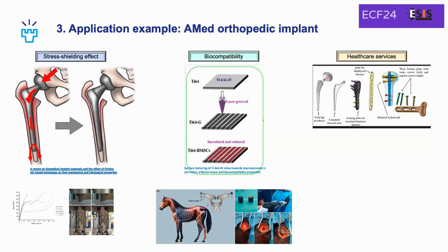So we hoped that the bone would attach to this open surface, and the best wish was that it would go through. Based on the specimens we took out from these happy horses, they were grown inside the whole implant. So it was not low density material anymore. It was completely filled with bone tissue.